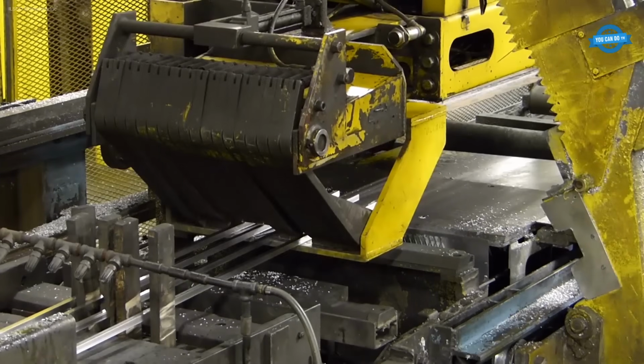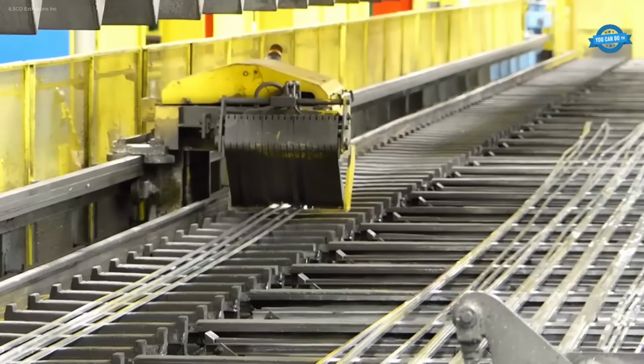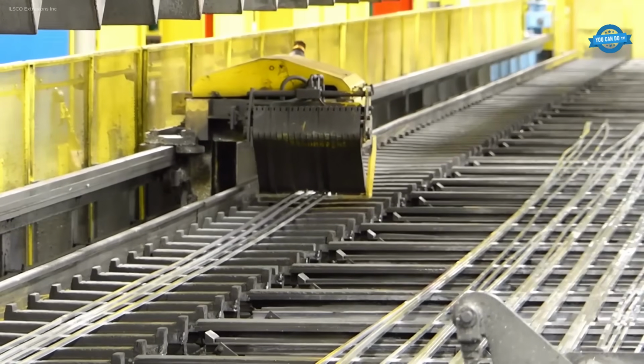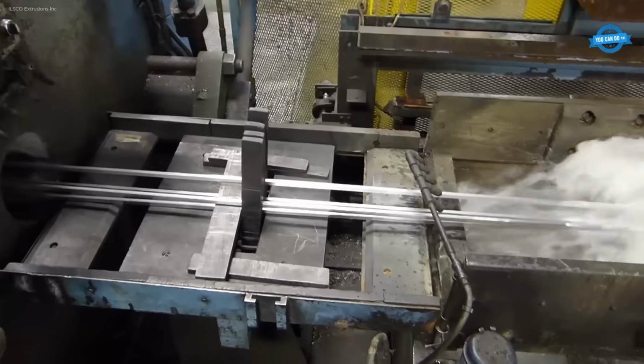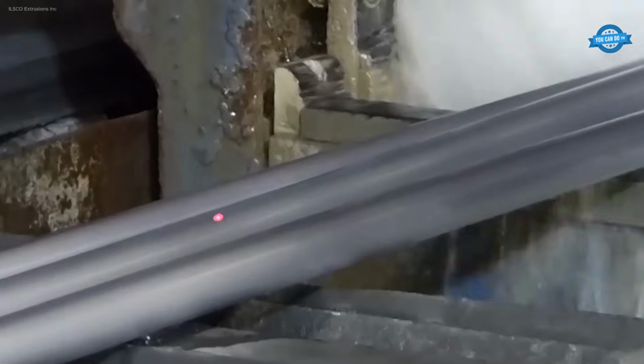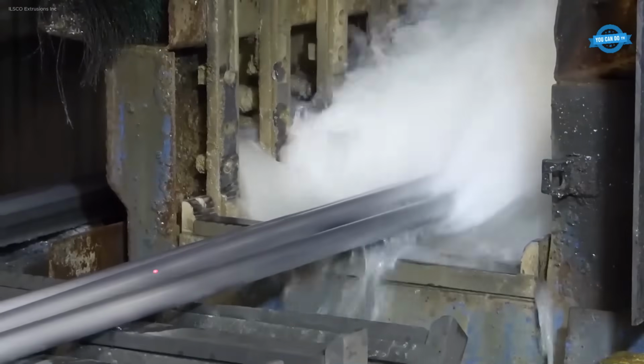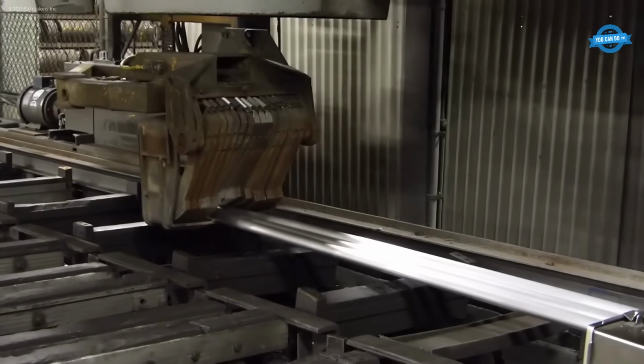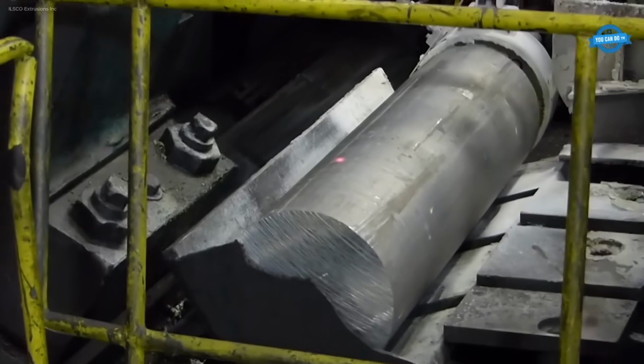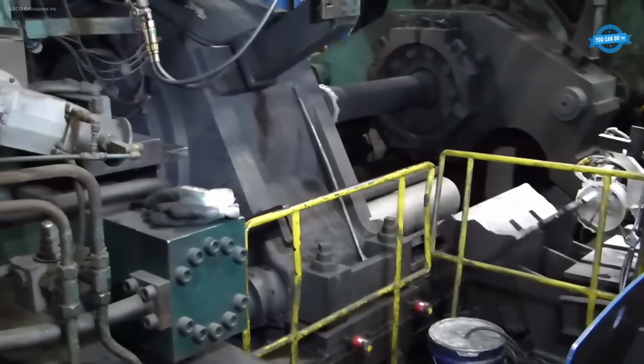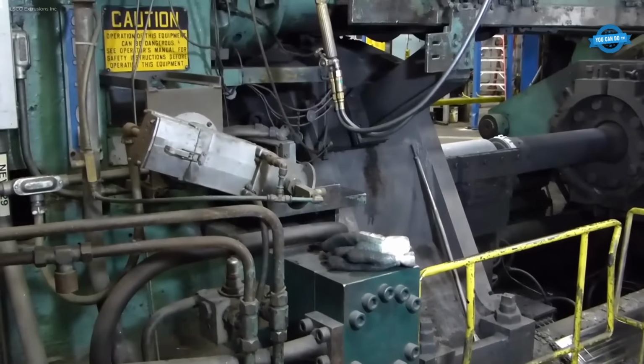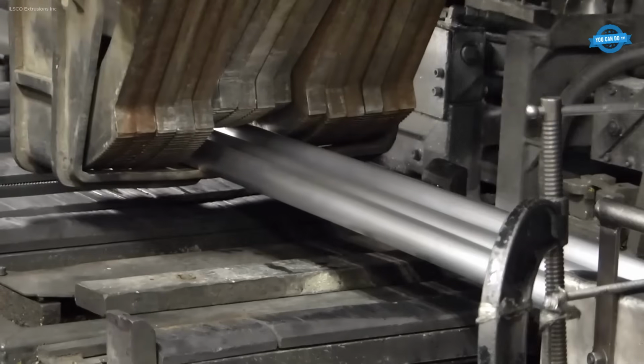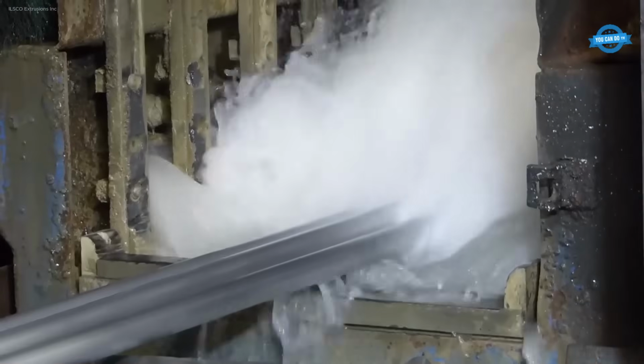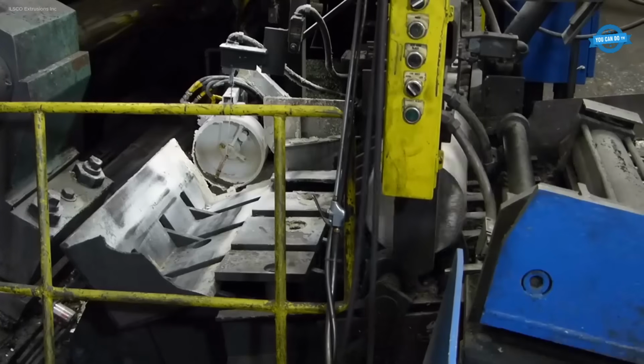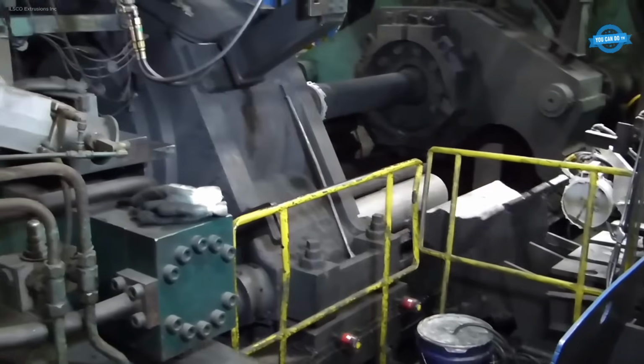As the profile exits the extrusion press, it enters a water quench to cool at a controlled rate, locking in specific mechanical properties. A puller system guides the extrusion across the run-out table, synchronized precisely with the press. Stretching follows, realigning and stress-relieving the profile before it's saw-cut to customer-specified lengths. Each extrusion is then artificially aged in ovens to strengthen the material. Final steps include deburring via vibratory finishing and optional surface treatments.